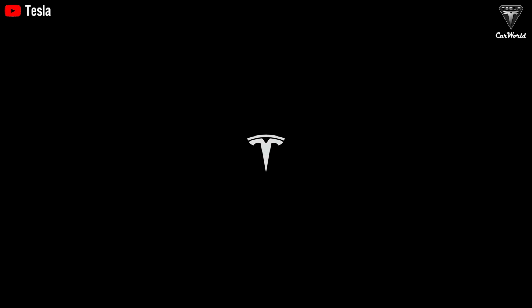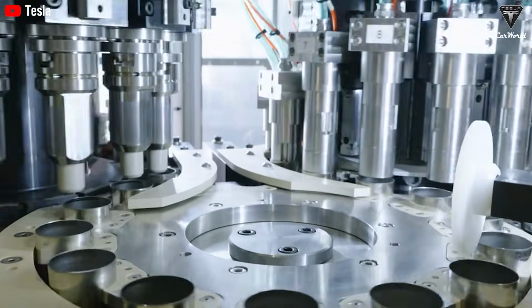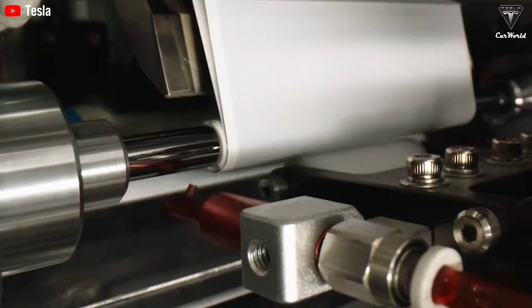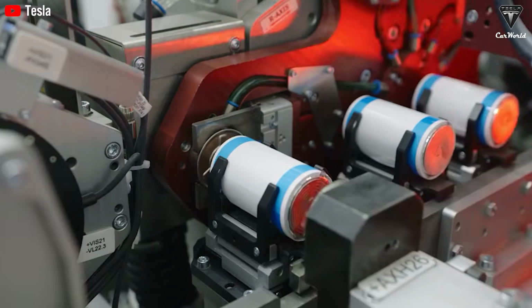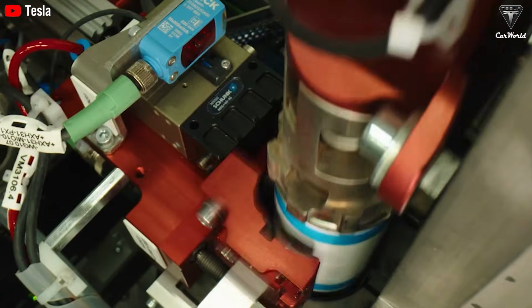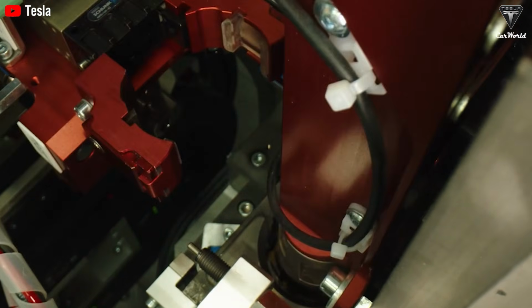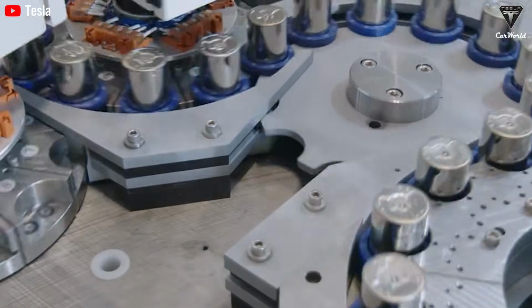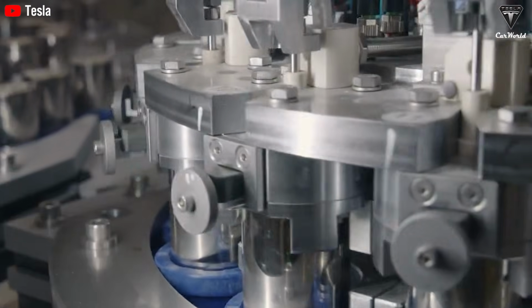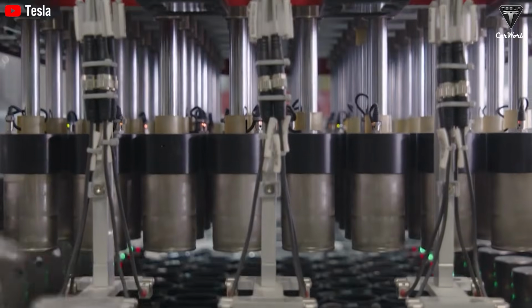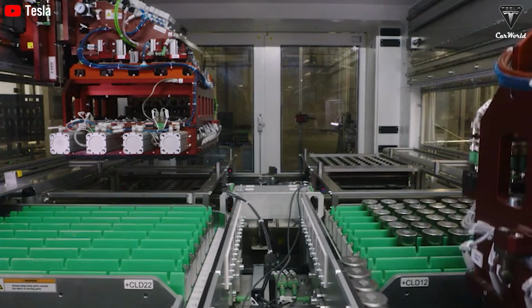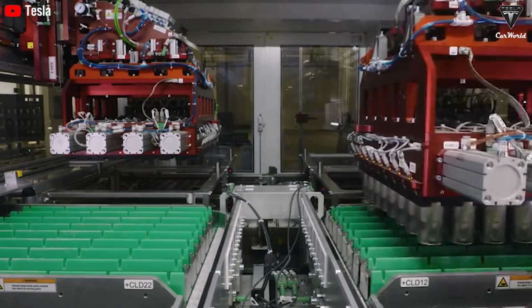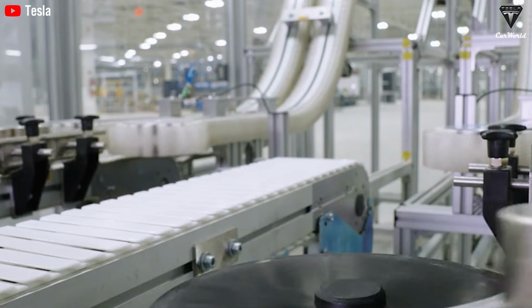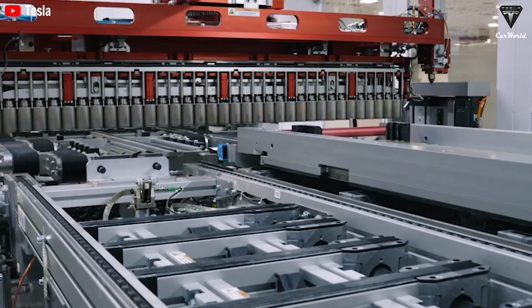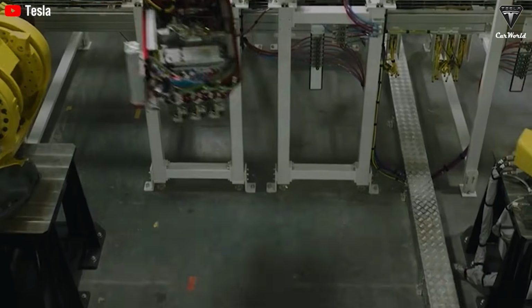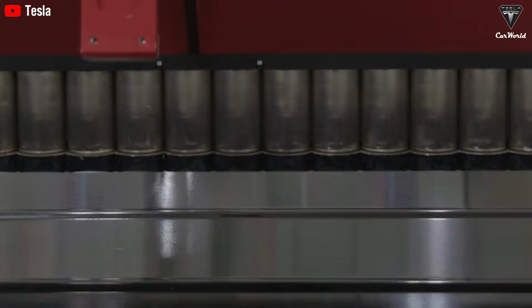Beyond safety, solid-state batteries promise a major leap in energy density. Today's lithium-ion EV batteries typically achieve around 250 watt-hours per kilogram and roughly 700 watt-hours per liter. Solid-state batteries, by comparison, are projected to reach close to 400 watt-hours per kilogram and over 1,000 watt-hours per liter. This increase comes from multiple factors. Solid electrolytes allow for thinner separators, reducing inactive material. They enable the use of lithium metal anodes, which have much higher theoretical capacity than graphite. They tolerate higher voltage cathode materials without rapid degradation. For electric vehicles, higher energy density translates directly into longer driving range, lower vehicle weight, improved efficiency, and more design flexibility. Smaller battery packs can deliver the same range, reducing cost and improving aerodynamics.